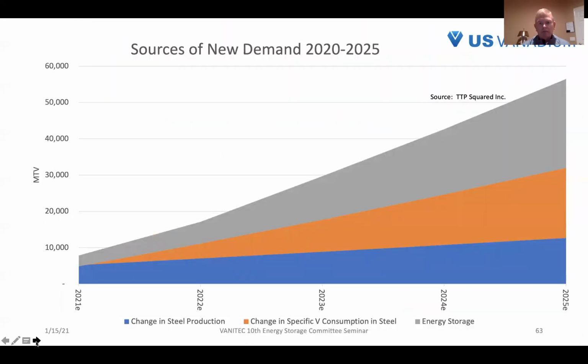If we look at vanadium demand in terms of new demand from 2020 onwards, this chart gives us an interesting picture. You see the lower level, the blue color here, is increase in vanadium consumption due to changes in steel production. When historically we look at consumption of vanadium, there's really two drivers, two variables that drive that. One is the absolute level of steel produced globally in the world. And the second factor is the specific vanadium consumption rate in steel, the kilos of V consumed per ton of steel produced. And that number basically is a reflection of what percentage of the steel actually contains vanadium.